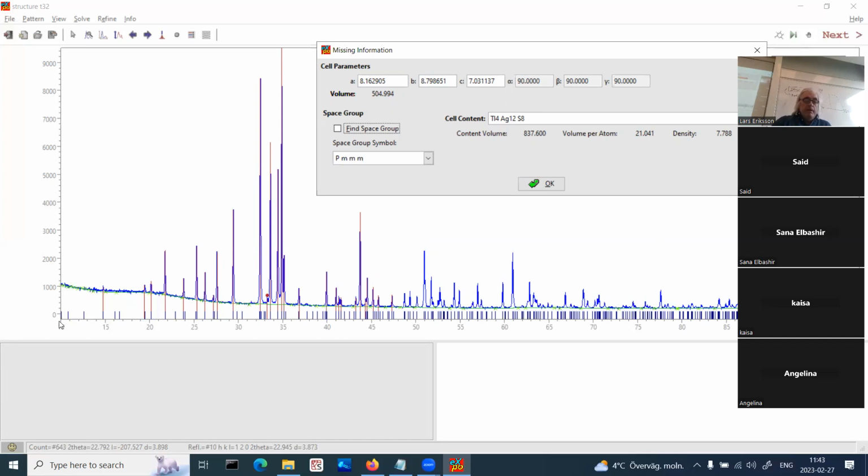With PMMM, all of the theoretical peaks are printed, and it's very difficult to gain some information. Every observed peak should, of course, be present in the list of theoretical peaks, but there must not also be a lot of theoretical peaks where we don't see anything in the observed pattern.